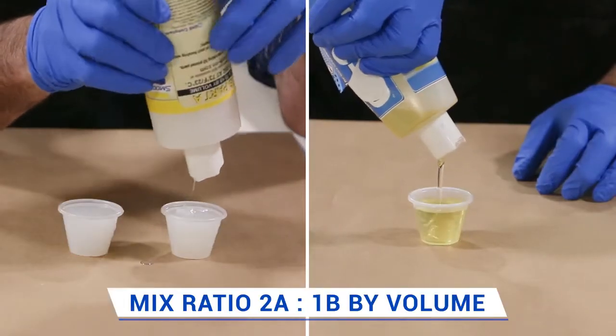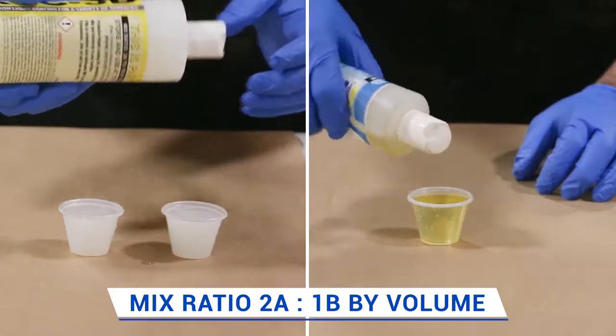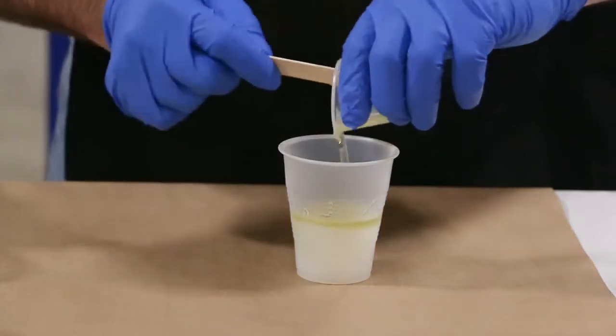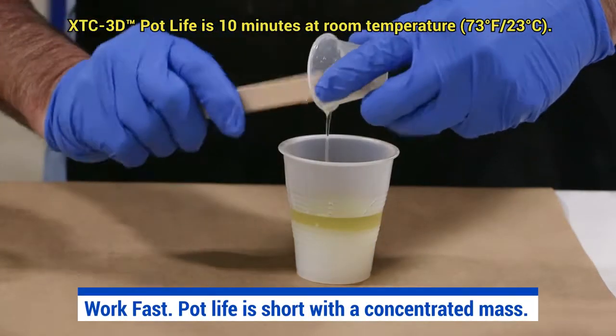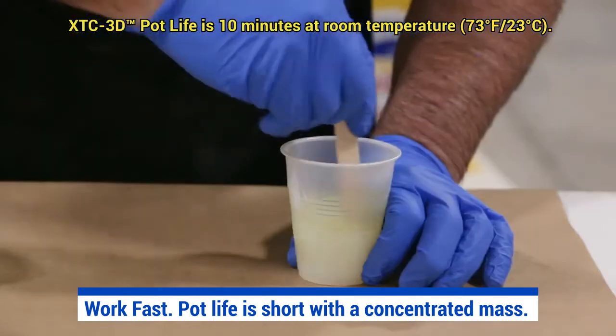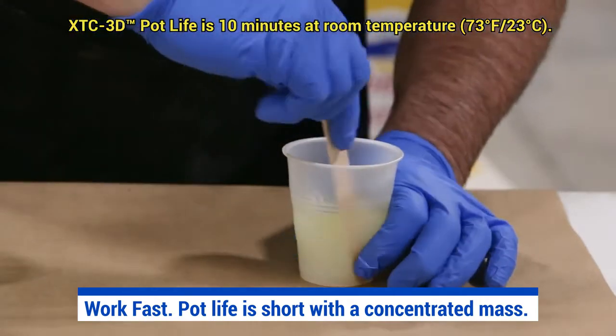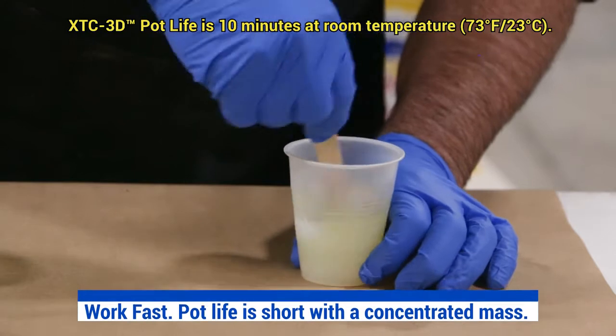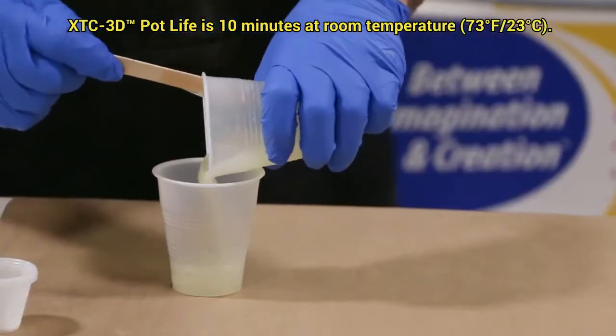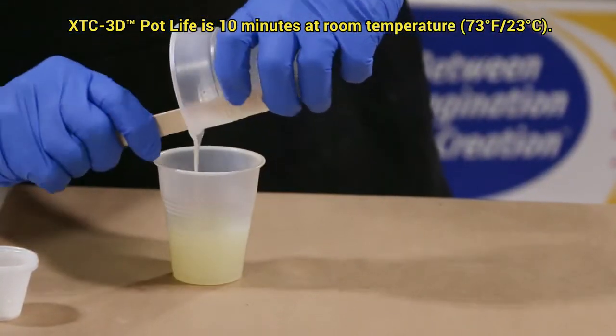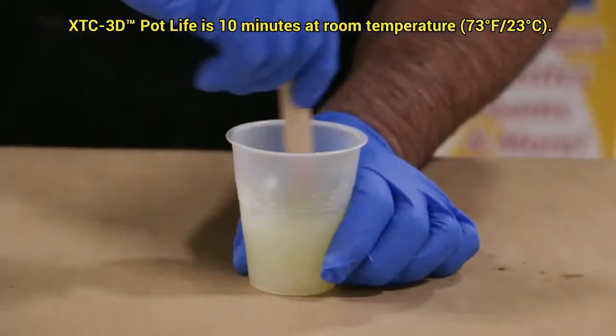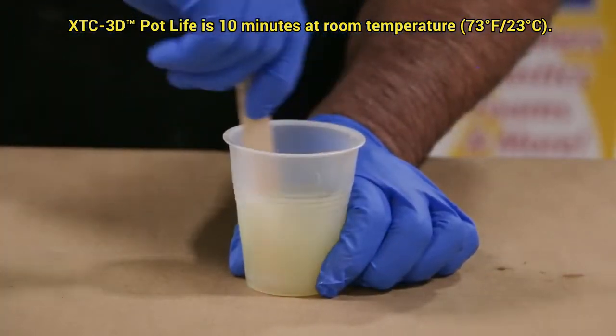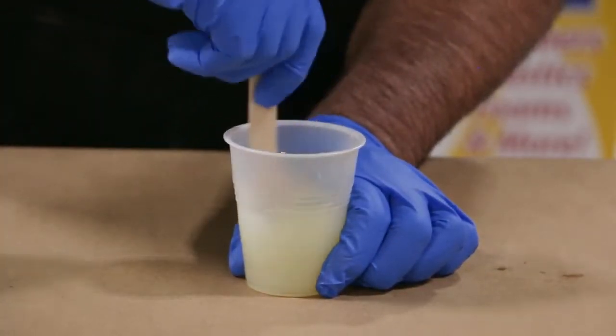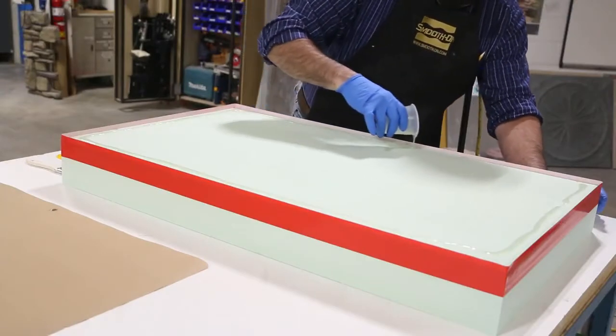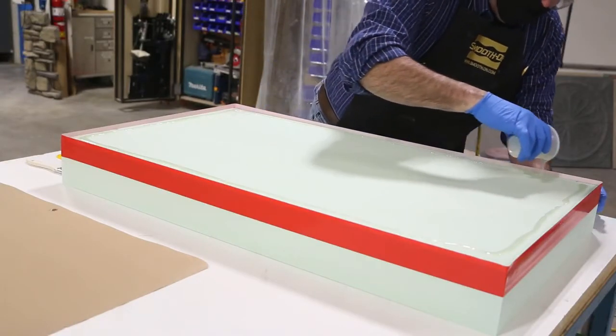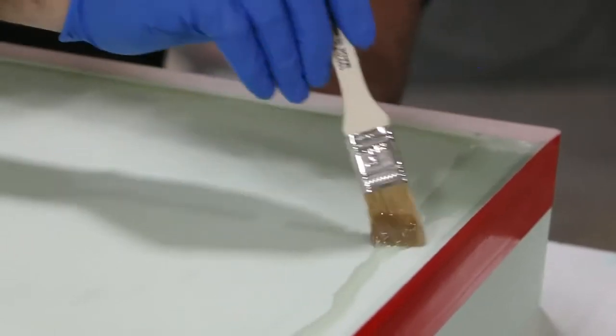Dispense A and B components 2:1 by volume into clean containers. Combine both components into a clean mixing container and mix thoroughly, scraping the sides and bottom to be sure to incorporate all the material. Transfer this mixture into another clean mixing container and mix again to ensure a thorough mix. After properly double mixing the material, immediately pour the material and brush or squeegee as evenly as possible.